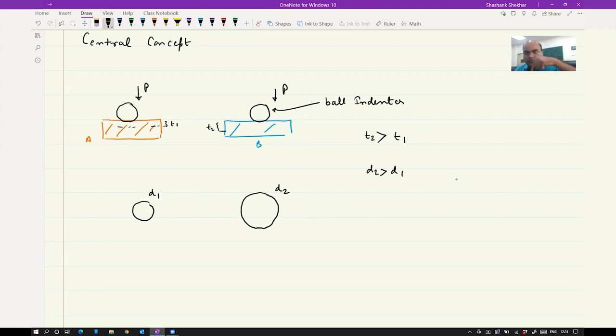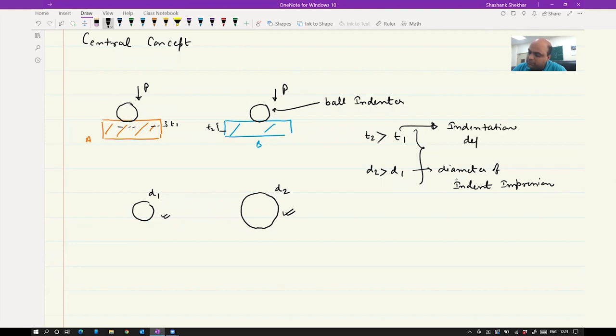So when you are trying to indent it, if you see the top view, you are going to see a circle. Okay, and since T2 is greater than T1, you're going to see a larger circle in alloy B. Okay, so if we have T2 greater than T1, so D2 greater than D1, where D is your diameter of indent impression. So this is your indent impression, both of that, these two, right? And T is your depth of indentation or indentation depth. Okay. So finally, you can write H1 greater than H2.